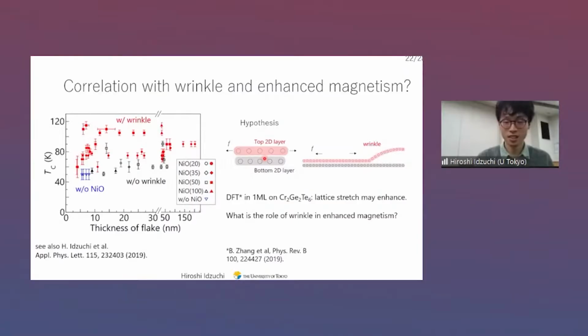So I have a very quick comment on the first question. Yesterday I reported our data on pressure-dependent chromium germanium telluride, where we found that compressive strain decreases the TC, decreases the magnetic anisotropy, and destabilizes magnetic order. From that, it could follow that tensile strain, stretching the lattice, would indeed stabilize magnetic order and enhance the TC. So that is somehow an argument which is put forward also by the speaker. Okay, thank you very much for that precious information. I'm glad to hear our study is consistent.